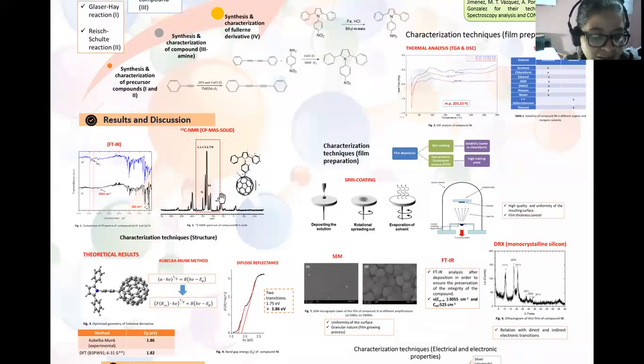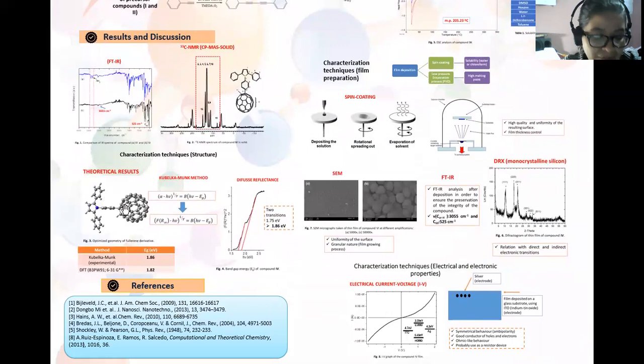The NMR study was carried out in solid state because of the strong insolubility of the fullerene derivative. The signals corresponding to the pyrrole fragment and fullerene were identified. Thereafter, the band gap energy value of the compound was determined from data obtained theoretically and experimentally. The value obtained by DFT was 1.82 electron volts, while the energy band gap obtained by the Kubelka-Munk method was 1.86 electron volts, so there is good correlation between both values.